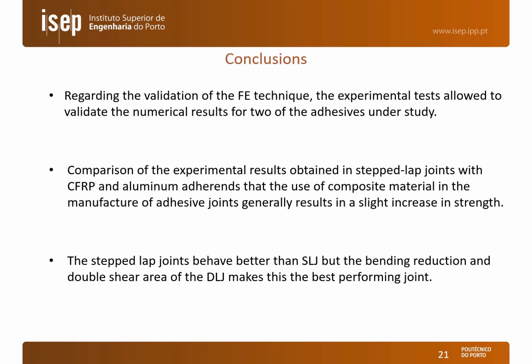Comparison between composite and aluminum joints typically gave a better result for the composite joints, except when interlaminar failure took place, which weakened the respective joints. And we also concluded that the step lap joints behave better than the single lap joints, but fall short of the double lap joints by a large amount, since this joint, although having a better stress concentration effect, also has double the shear area. So this results in the best results between the three types of joints.